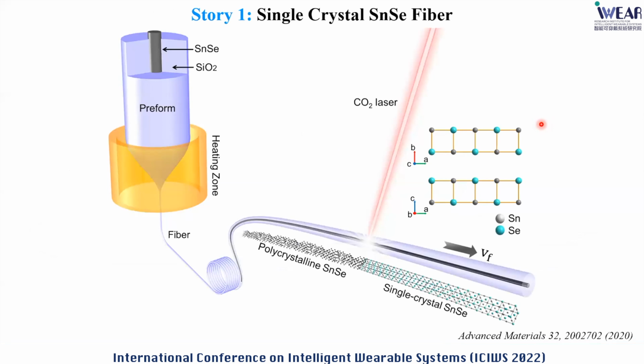The first story is to achieve so-called single crystal tin selenide fibers. Here, we use this type of preform-to-fiber fabrication technology. For example, in the core, we put tin selenide. The reason that we choose tin selenide is simply that it is a star material for thermoelectric applications, and especially for single crystal tin selenide, it's fundamentally challenging to make it a single crystal, and even more challenging to make that into different types of devices. So in order to show the feasibility of our technology, we choose this semiconductor, which is rather challenging to make into a single crystal.